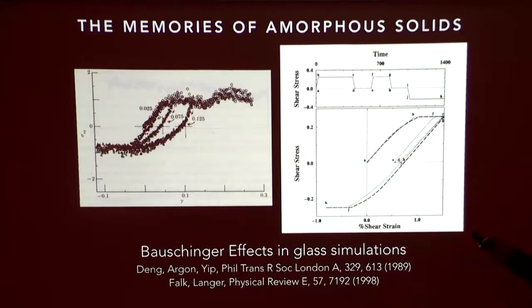This one was done by applying the stress and measuring the strain. So this was ramp up, hold the stress, lower it, hold the stress at the same level again, lower it, then hold the stress in the opposite direction. But you can see these things also under strain control. But that's just a theoretical picture. This is, well, no, this is MD data plus theory.